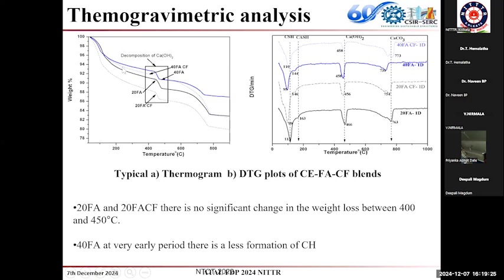Similarly, here what we have done is, when we are going for high volume replacement, for 20% replacement, we added this CF, a chemical admixture, that is calcium formate. So how is it altering and improving the formation of calcium hydroxide?